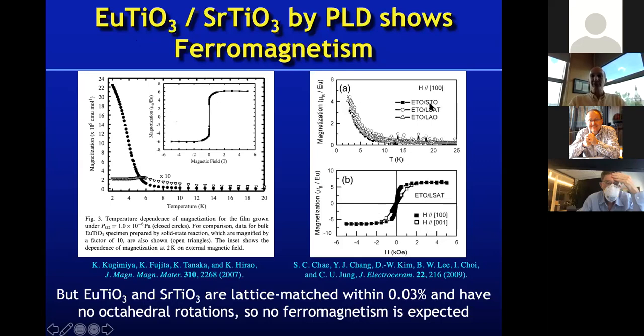This other group here, in fact, tried it not only on strontium titanate, they tried it on lanthanum aluminate and LSAT. So things with totally different strains. No matter what they put it on, it's ferromagnetic. And you can see clear hysteresis loops. Now this, in one sense, points to the fragility of navigating the landscape in quantum materials. To me, the excitement of oxide quantum materials is that you have nearby ground states in energy. And it's nice to be able to go from one to another.